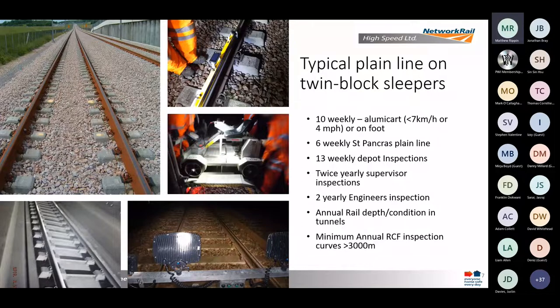We use the Alumicart for a lot of our inspection, which allows us to cover large distances in a single night and reduces fatigue for operators — although there have been a few reports of things getting a little sleepy on some of the longer runs, particularly on chilly nights. A lot of our historic geometry defects have been driven by poor weld profile — generally high spots on welds, whether compressed following installation or poorly finished. We use the Recti Rail system to identify those high spots and profile them out, seeing significant improvement in geometry performance as a result.